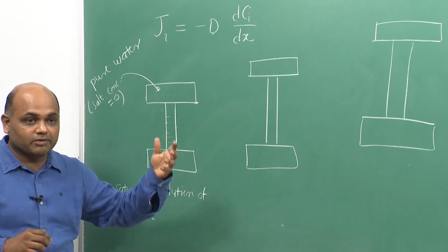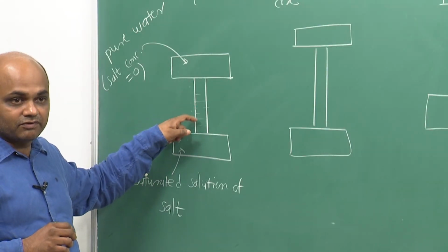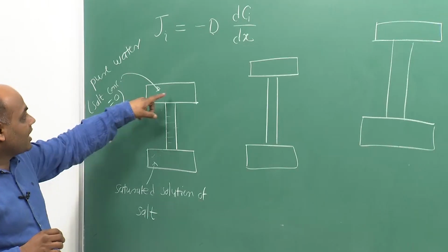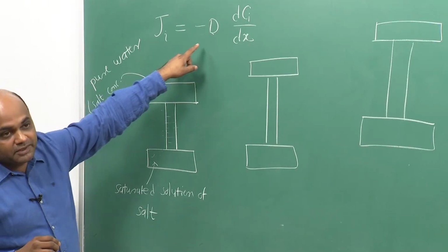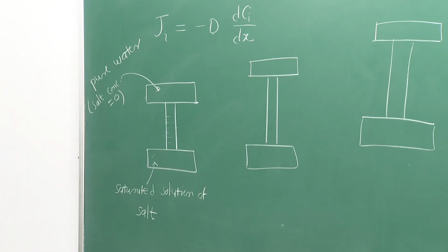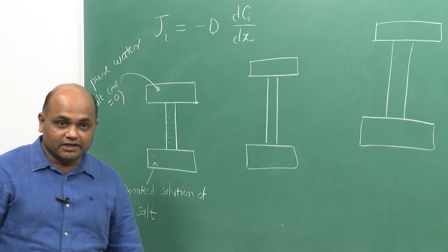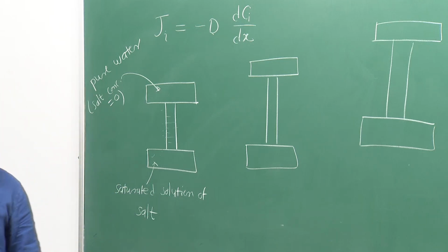So, that there is no accumulation or depletion of the matter in that plane, right. So, the flux should be constant, and from that we can determine this constant D, or in his notations K, he could determine the constant K, and he saw that this constant K was independent of the length of the tube,